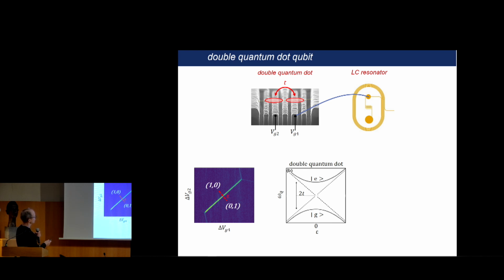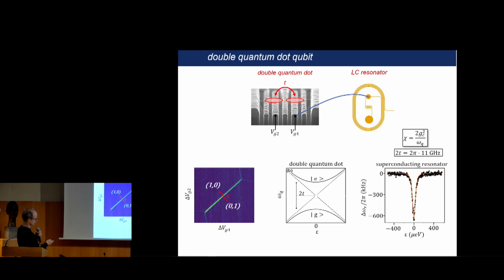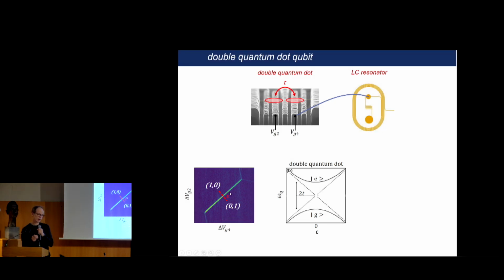Okay, so I told you that we can use this V-gate 2 and V-gate 4 to change the number of electrons in the two dots. And here what I show you is that it's possible to move the electron from the left dot to the right dot here. Okay? So we move the system along this red line by playing with these two gate voltages. And when this red line intersects here the green line that we measure, we have that the left dot and the right dot are in resonance. So we have the potential of the two dots that are in resonance. The two dots hybridize, and then it creates a qubit.